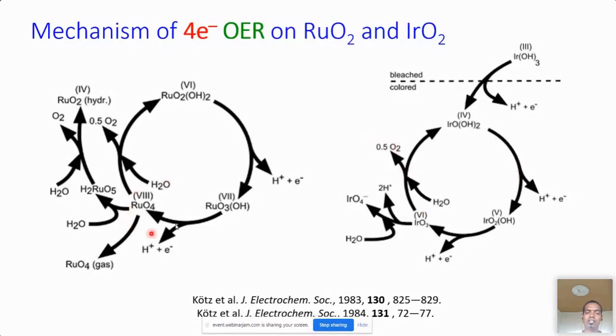But when you compare the toxicity, iridium is relatively better than ruthenium. These 2 mechanisms were actually revealed by Kötz et al. in the 1980s, even before I was born. So this is very old material, and these 2 materials have ruled for more than 3 decades in this field of water electrolysis as anode catalyst.